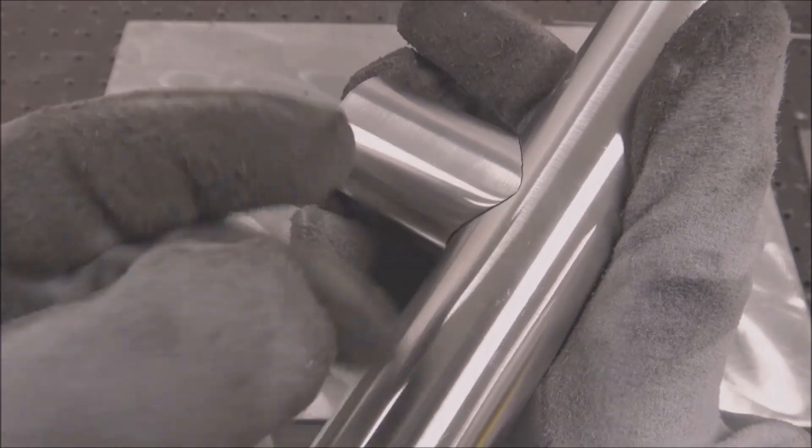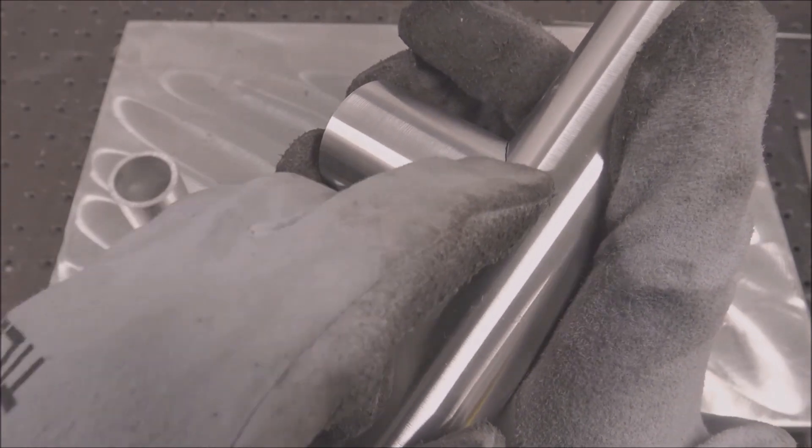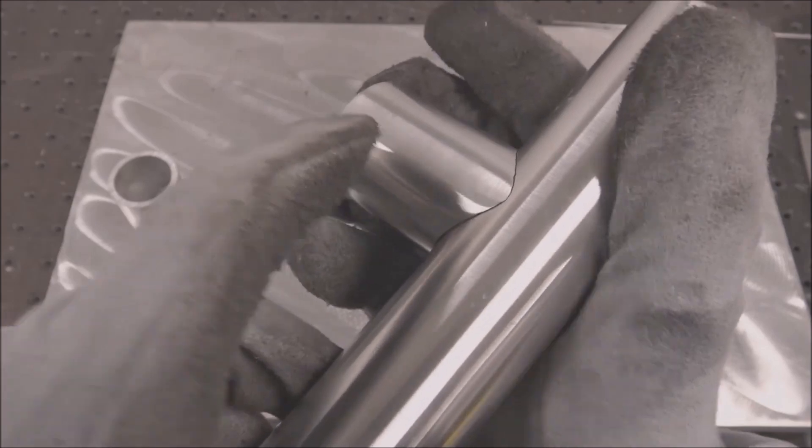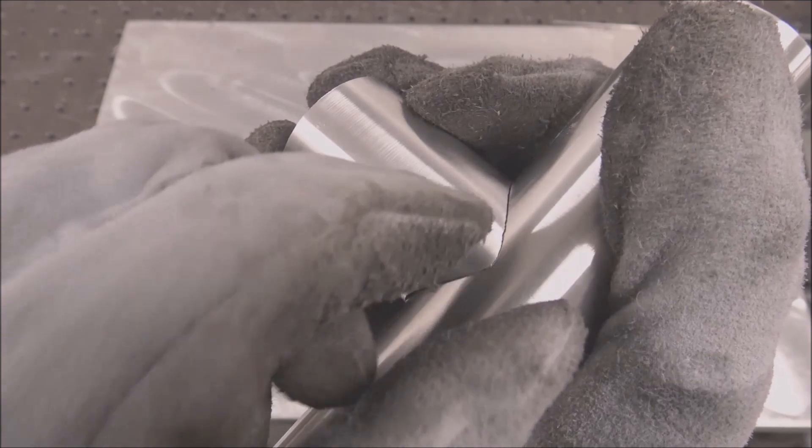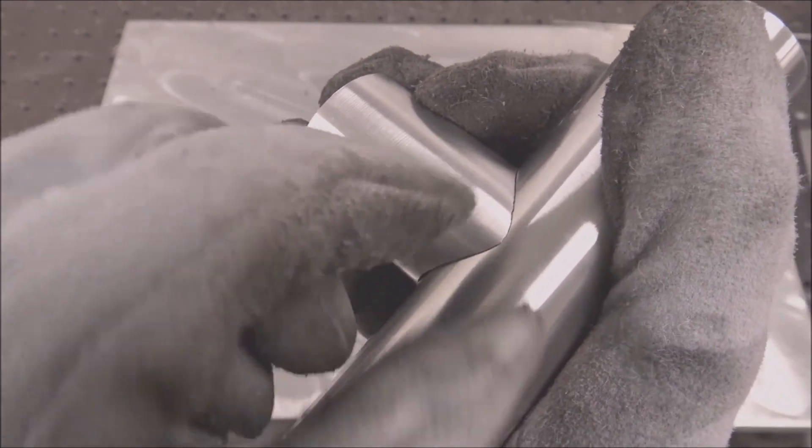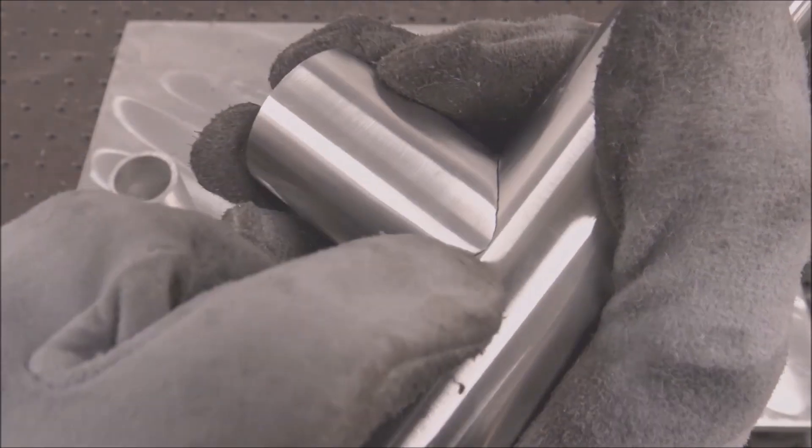And then you won't want to, instinctively you're not going to want to put as much filler rod in there because you don't want it all humped up and ugly. So percentage-wise, you're getting too much 6061 in the weld joint versus your filler rod. And if there's not enough filler rod, it's really prone to cracking.